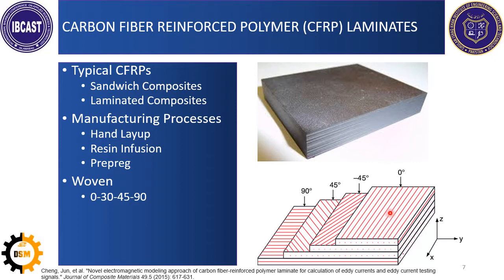The orientation of the fibers is also important to define the final characteristics. So here you can see the fibers are oriented at 0 degree as compared to the x-axis. The second ply is at -45, the third one is +45, and the fourth one is 90. These orientations change the properties of the components, and that is defined by the number of plies and these orientations. So both of these two things define the final properties of the composite laminates. So how do you define what is the final strength you are going to get? This is based on the macromechanics of the laminate.